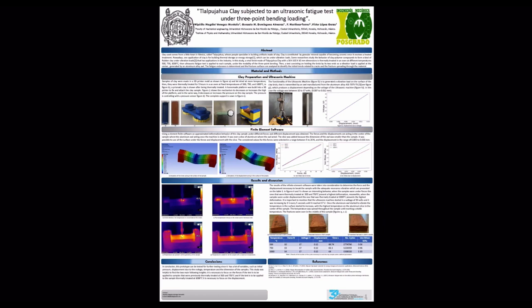The clay used comes from a little town in Mexico called Tlalpujahua, whose people specialize in building artifacts made of clay. Clay is constituted by granular minerals capable of becoming ceramics once it receives a heat treatment. In this study, a small brick made of Tlalpujahua clay with a specific dimension is thermally treated in an oven at different temperatures: 500, 750, and 1000 Celsius degrees. Then an ultrasonic fatigue test is applied to each sample, under the modality of 3-point bending.